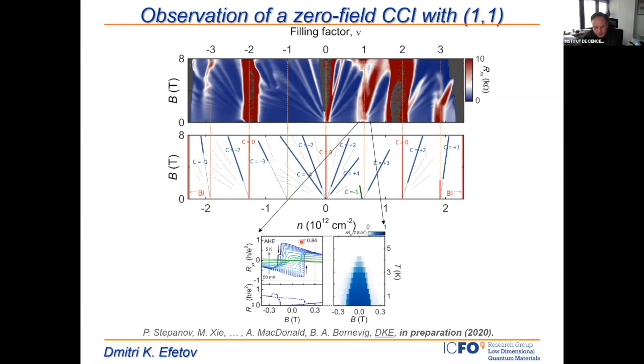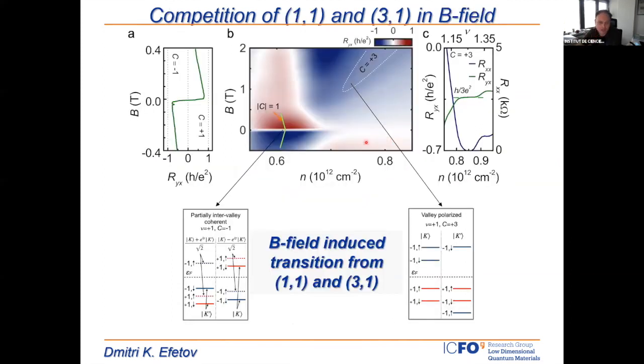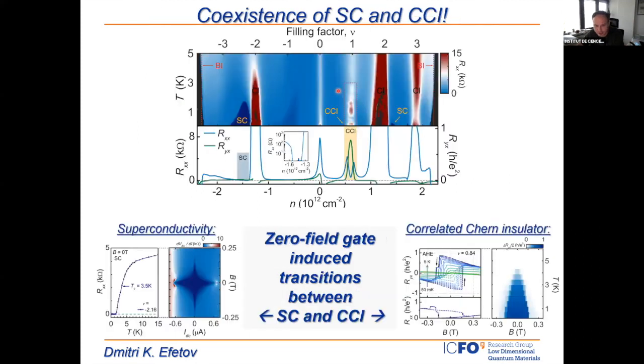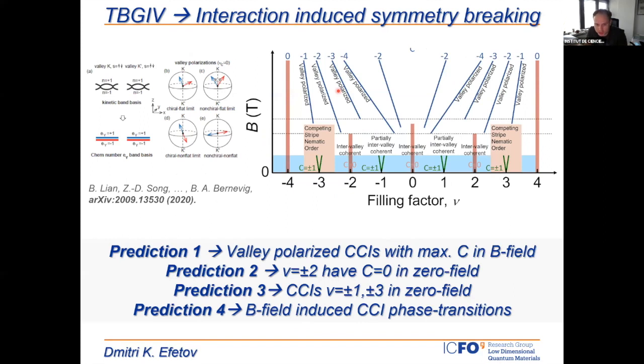And what we can also study in this type of situation is the phase transitions which are going on in magnetic fields. Because for this particular case here, as I mentioned, we observe a magnetic state with a Chern number of 1 at zero field, but when we go to higher magnetic fields, we see that the state disappears, and we go over again to a Chern number of 3. So I'm sorry if I'm a little fast right now. I went to a different topic, but let me explain a little bit better what is the theoretical picture which we are dealing with here.